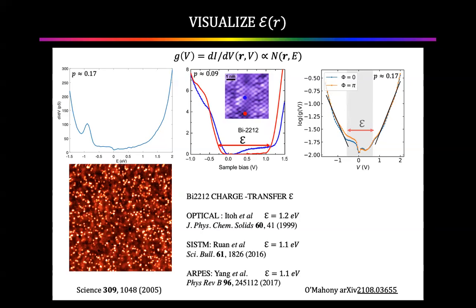You would need more detailed predictions of the integrated density of states as a function of energy to be sure. But it certainly is the energy gap between the top of the lower band and the bottom of the empty band. That's a fact that you can just see from the data. So in our study, that's the distance we're measuring: the energy from the top of the lower band to the bottom of the upper band. And this is a logarithmic scale of the density of states. The density of states takes off like a rocket. It's reasonably well defined how big that displacement is.